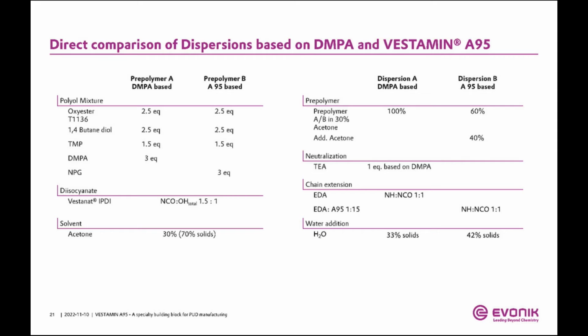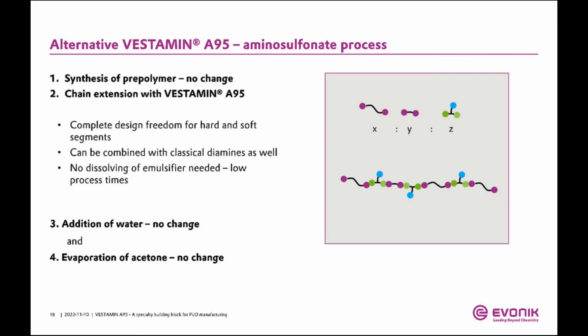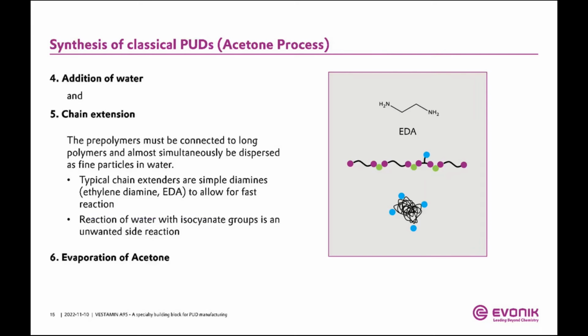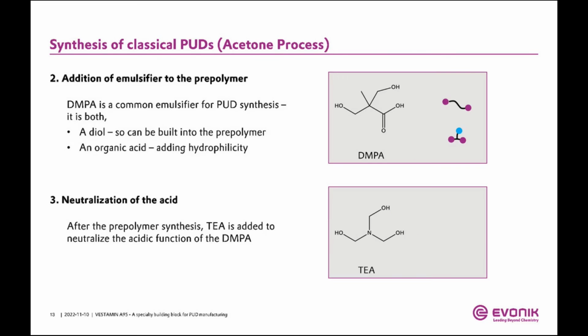Yeah, interesting question. Just from the chemical properties, it can be easily explained why we have this lower water resistance. When we go back to the chemical structure, when I have the DMPA, the hydrophilicity of the acid is relatively low. It's only at the point when I add the amine, which causes my acid to turn into a salt, that causes the real hydrophilicity, right? So the salt is the big hydrophilic component.